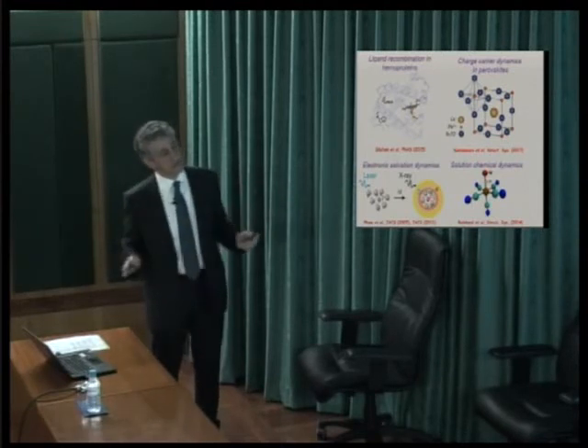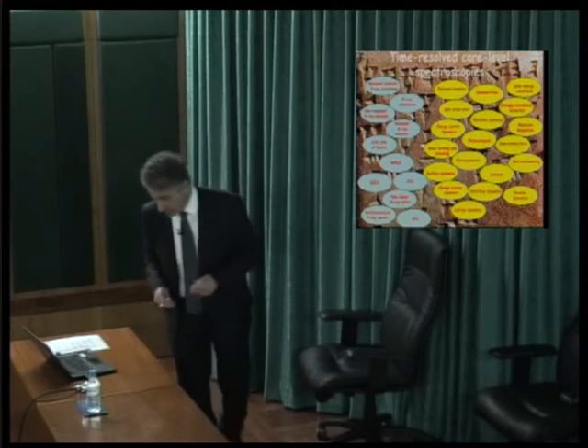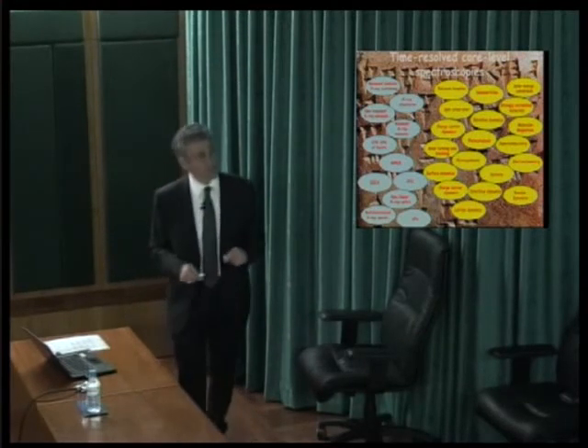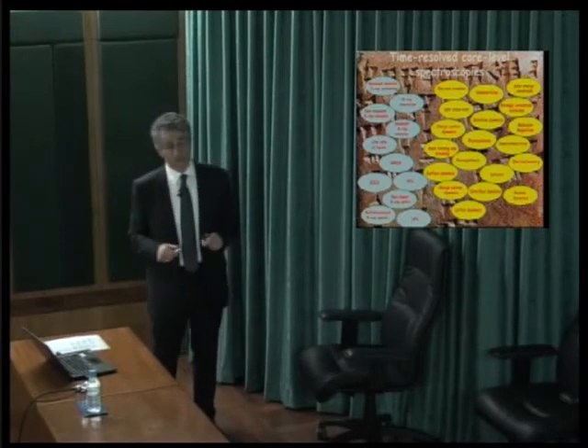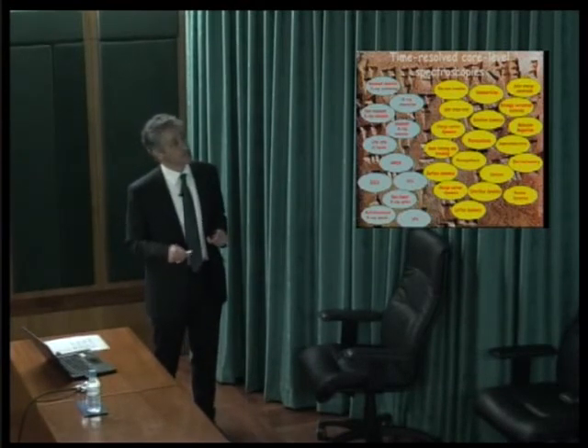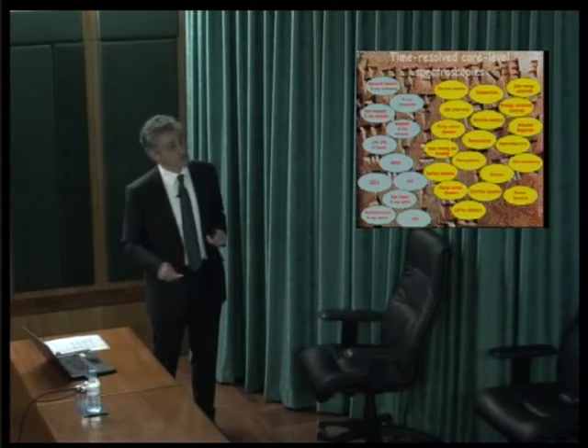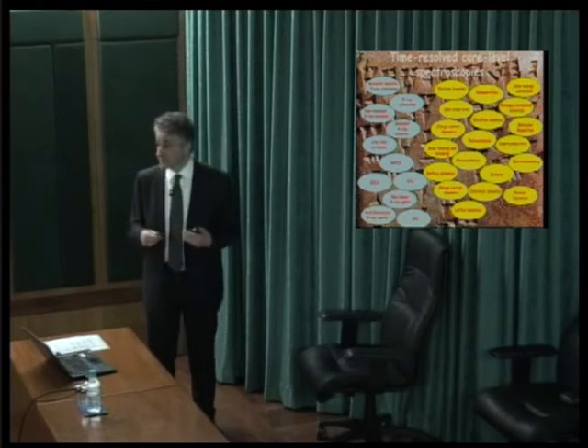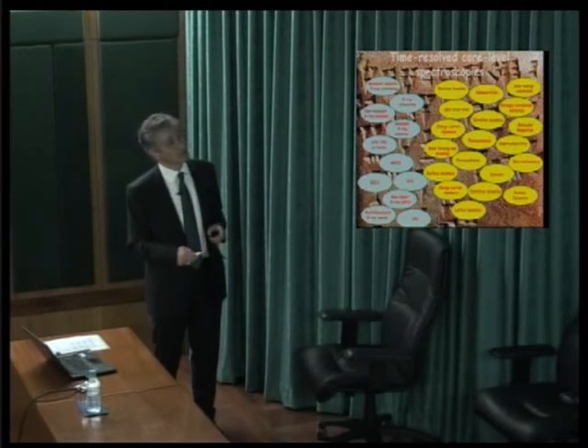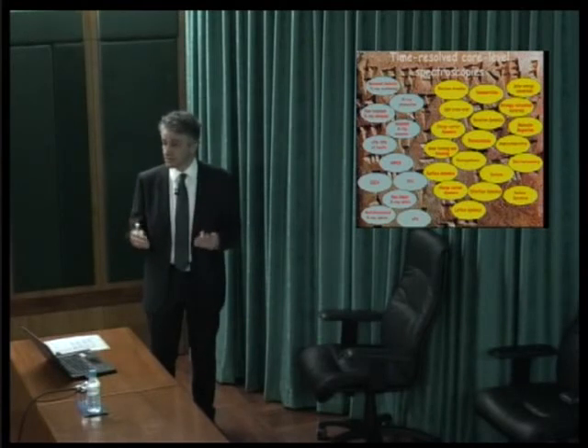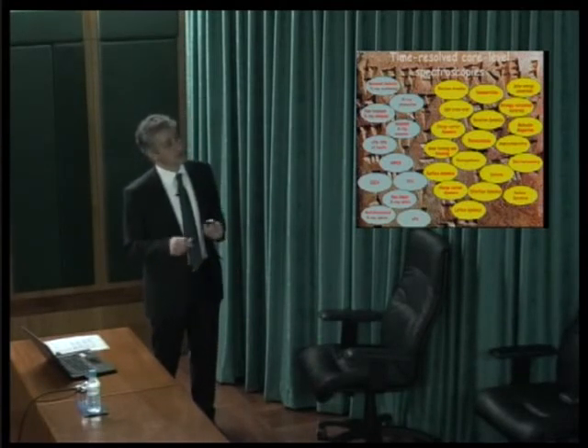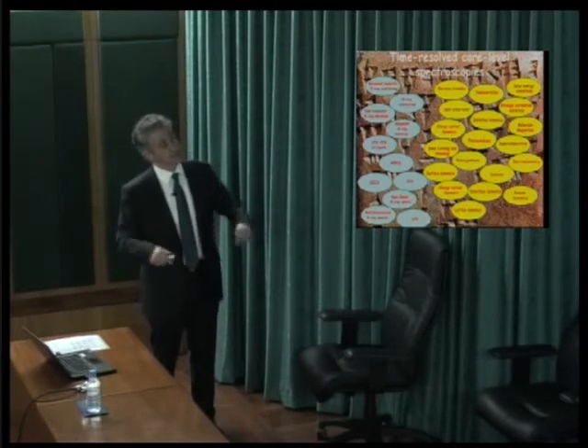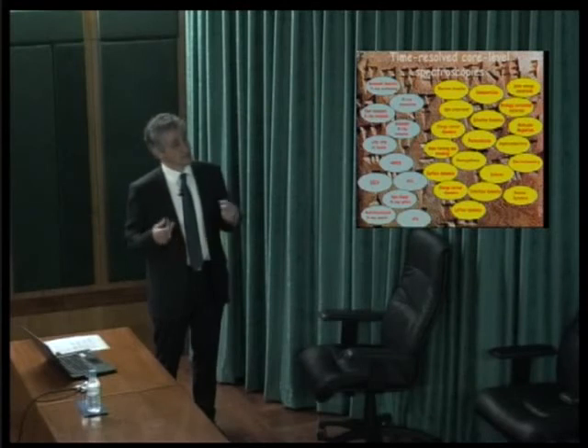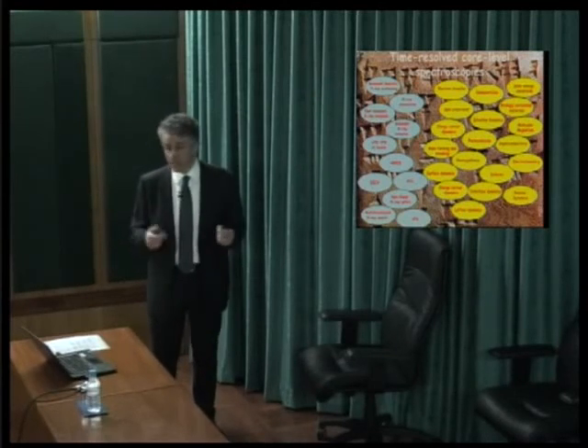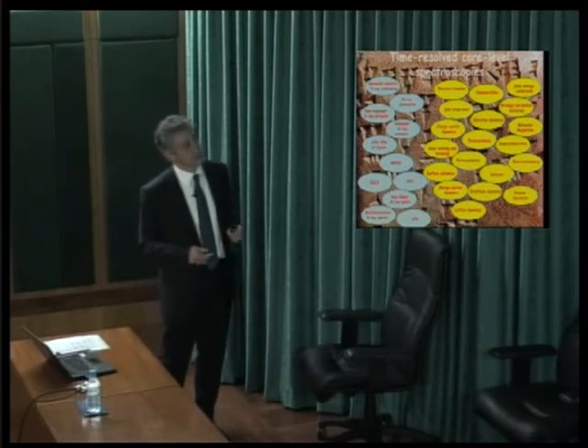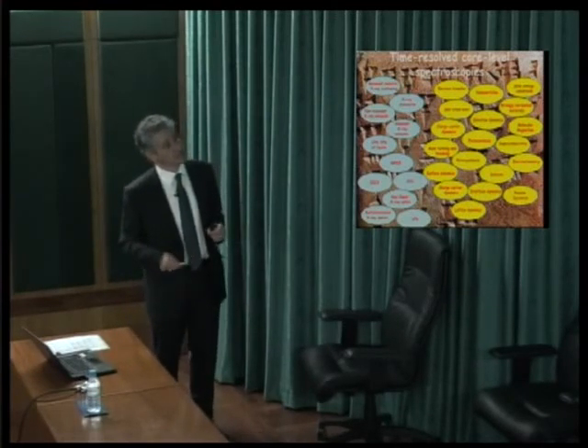This is, in a very brief way, the results we have. I didn't mention everything, but I want to stress now that these time-resolved core level spectroscopies are gaining momentum. There are many, many different techniques, as I said, with different acronyms. Resonant inelastic X-ray scattering is a type of X-ray Raman technique, which is extremely powerful, especially for ordered solids when you're doing condensed matter physics, because you can resolve in momentum space. And if you do it in a time-resolved fashion, you can also get the time evolution of the system. The first paper was published a year ago, and it was results from the free electron laser in Stanford.